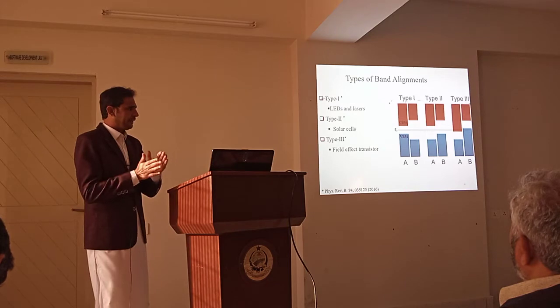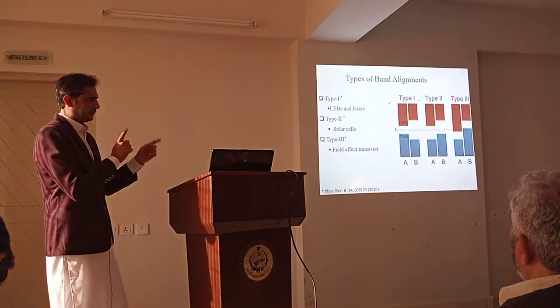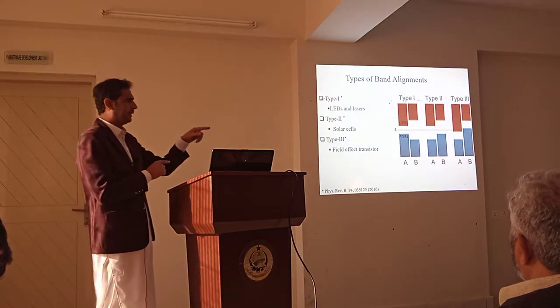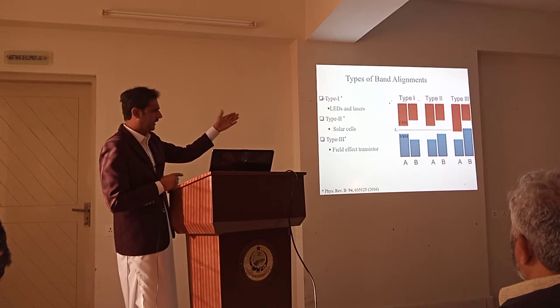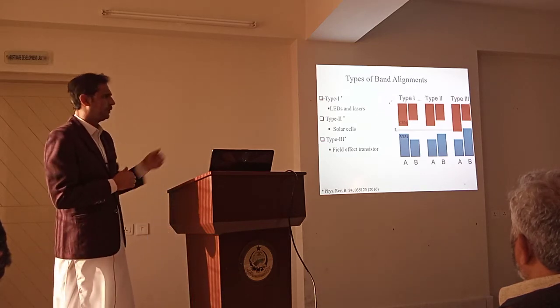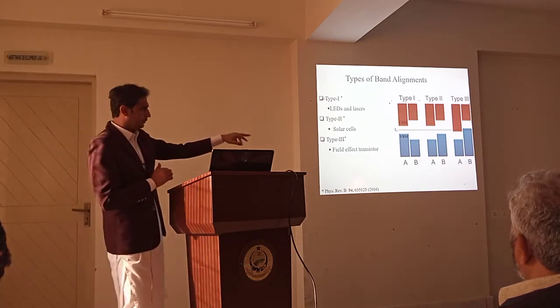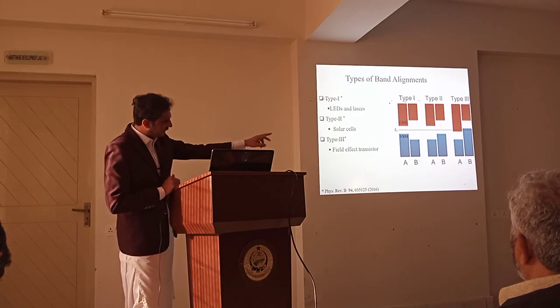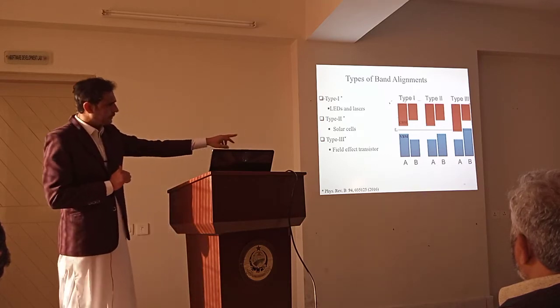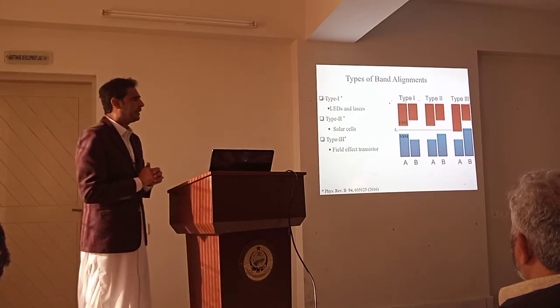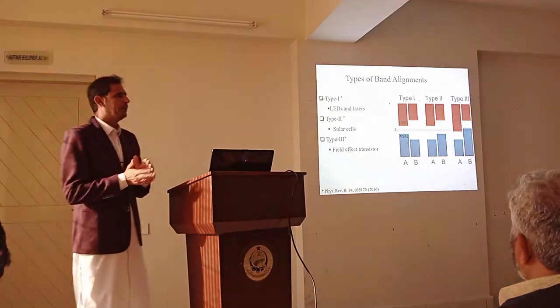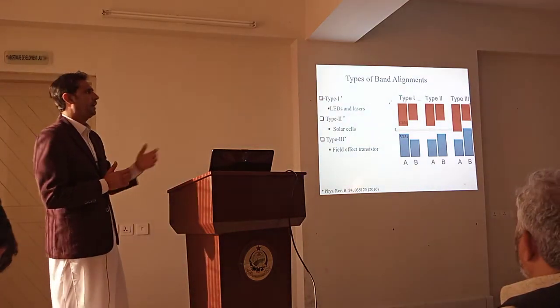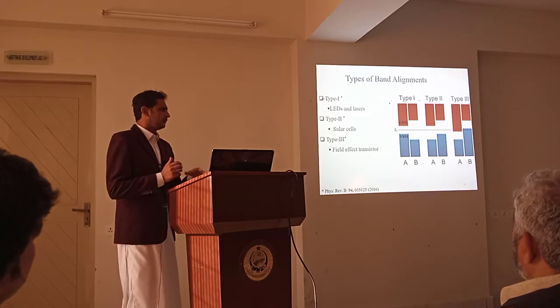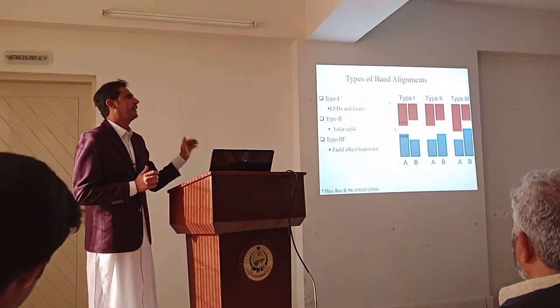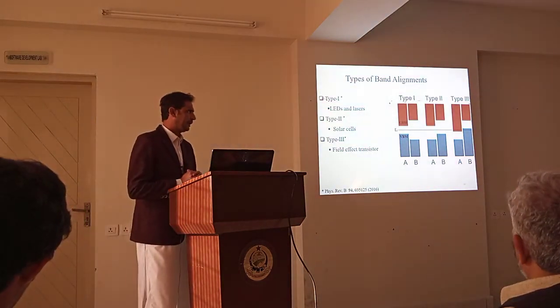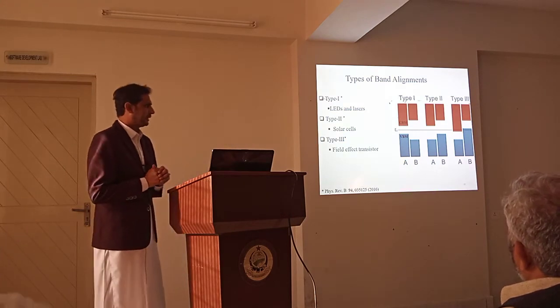And when the VBM is from one monolayer and the CBM is from the other monolayer, it is type 2 band alignment. In this figure, the above line is the conduction band minimum, while the below is the valence band maximum. We can see for the other one, the VBM is from the B monolayer, while the CBM is from the A monolayer. It means that the VBM and CBM lie in different monolayers. While for type 3 band alignment, either monolayer A or monolayer B crosses the Fermi level, so it will be type 3, which is used for field effect transistors.